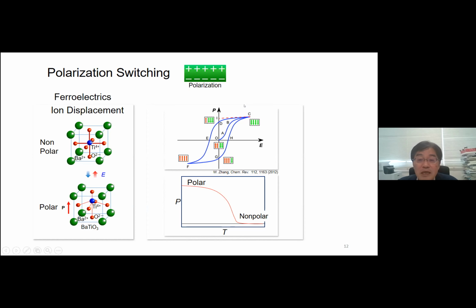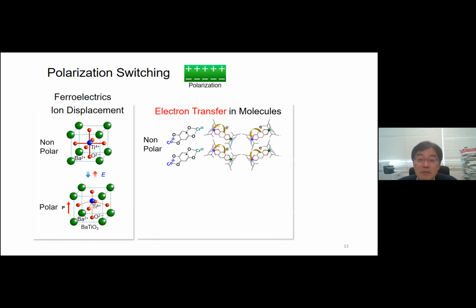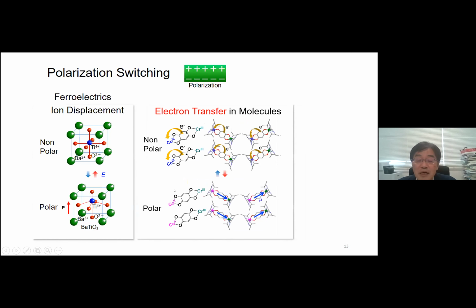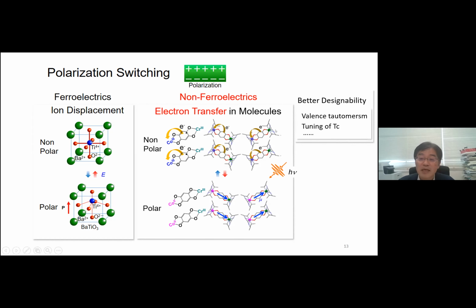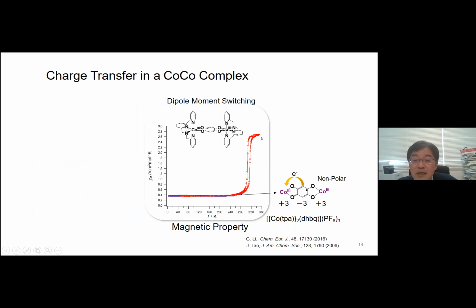And in this study, we aim to synthesize new polarization switching material using electron transfer. As shown here, electron transfer is the source of polarization instead of ion displacement. And the advantage is electron transfer can be directly controlled by photoirradiation. And we also use non-ferroelectric compounds, Valence Tautomeric compounds, because of its better designability. And now we talk about polarization switching material using electron transfer. And to realize polarization switching using electron transfer, we focus on this cobalt Valence Tautomeric compounds.